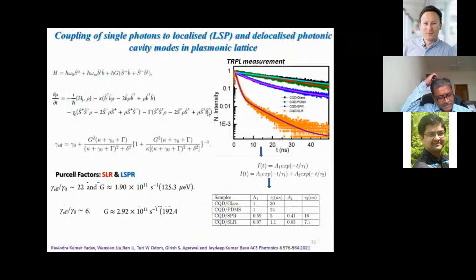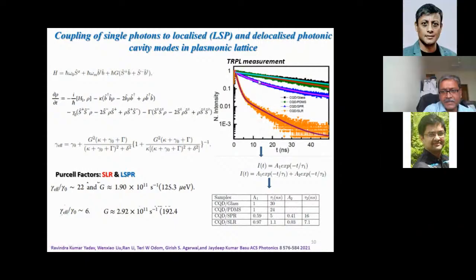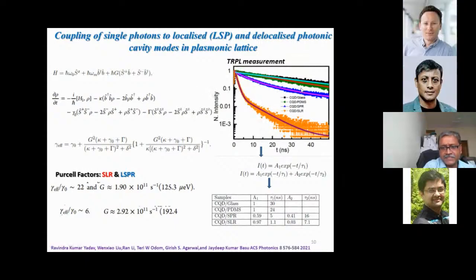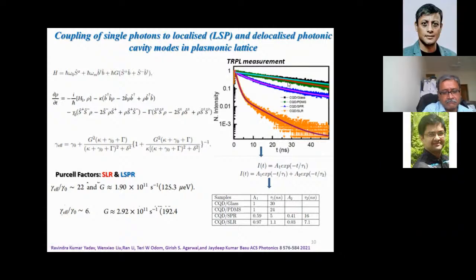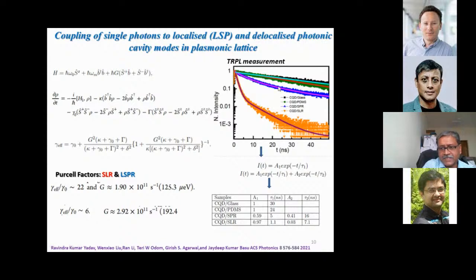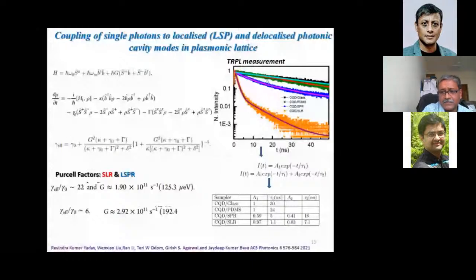So I'll show two results here. The first one is a time-resolved photoluminescence measurement. This is for these isolated quantum dots. If you take glass or some trivial substrate, you get a nice single exponential decay, and you can extract the time constant for the decay of photoluminescence of these quantum dots. These are single quantum dots, but from this measurement you cannot tell. But the point is that you get a nice relaxation curve, which can be easily fit with a single exponential.